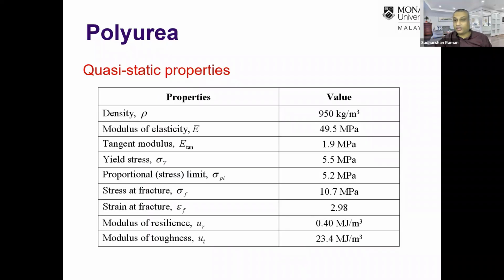And then these are the quasi-static properties that were recorded during the experiment. The density was about 950 kilograms per meter cubed. The elastic modulus was close to 50, 49.5. And then the strain at fracture was 2.98. And as you can see, the material exhibited strain hardening behavior after the yielding point.